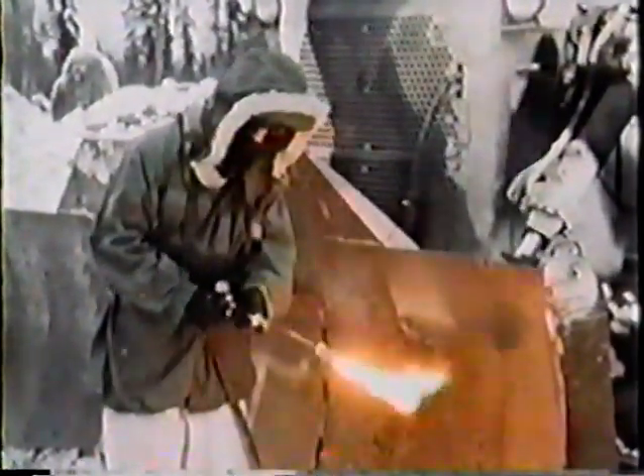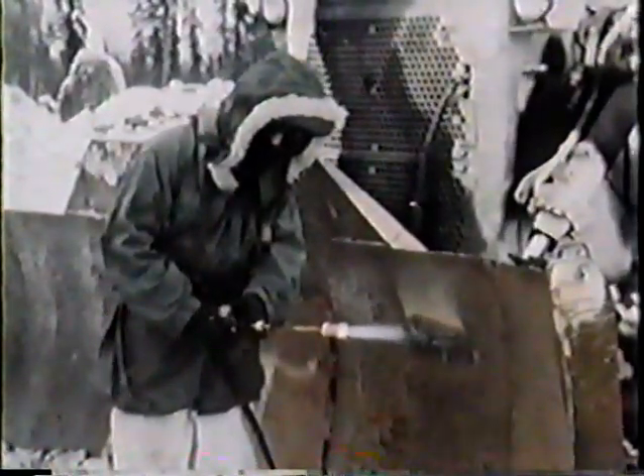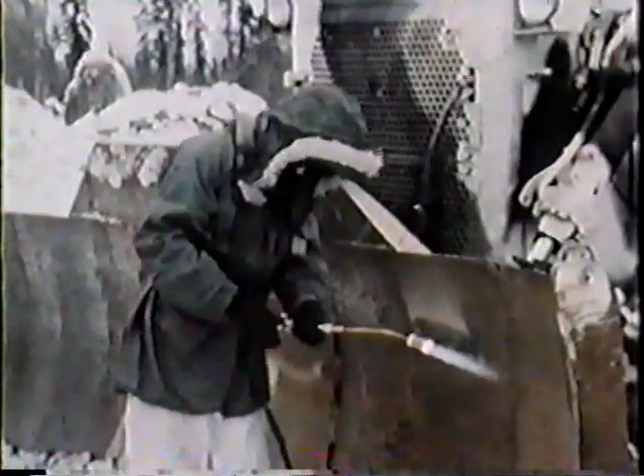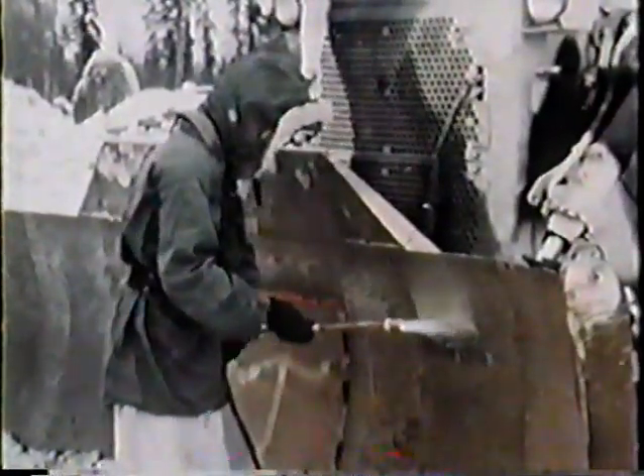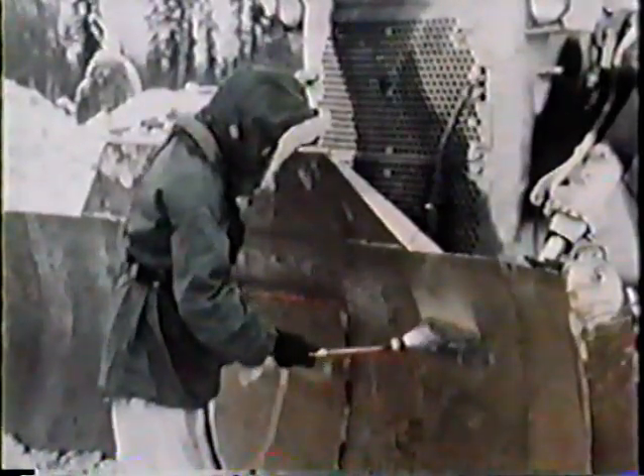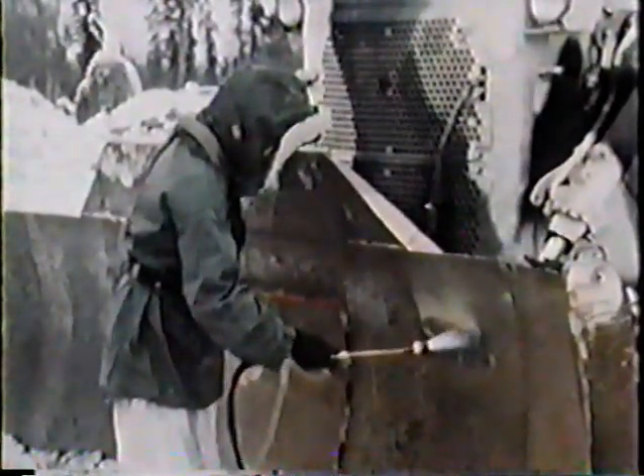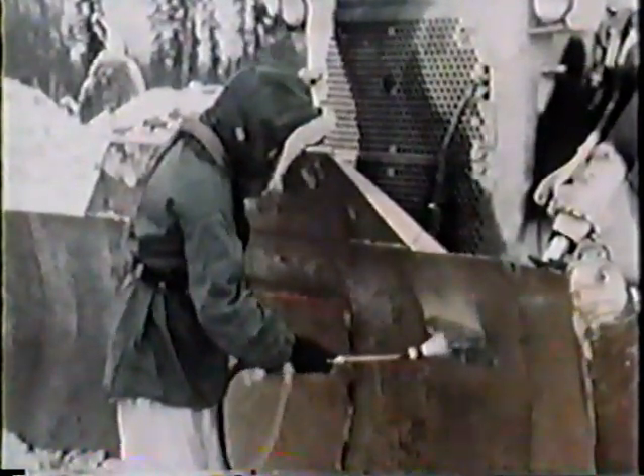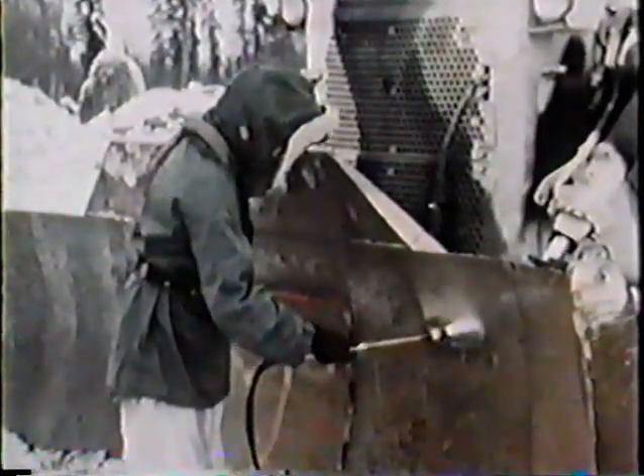After you've completed the welding repair, the next step is vitally important: post-heating. Keep torching for post-heating until the temperature is at the point recommended by the manual, and then insulate the area for gradual cool down and stress relieving. The manual shows post-heating temperatures for low and medium carbon steels. They should be no higher than preheat temperatures.